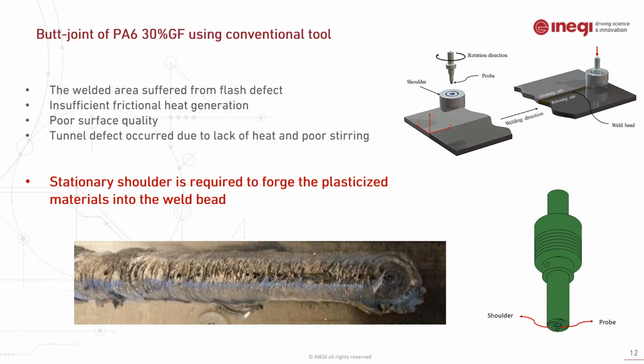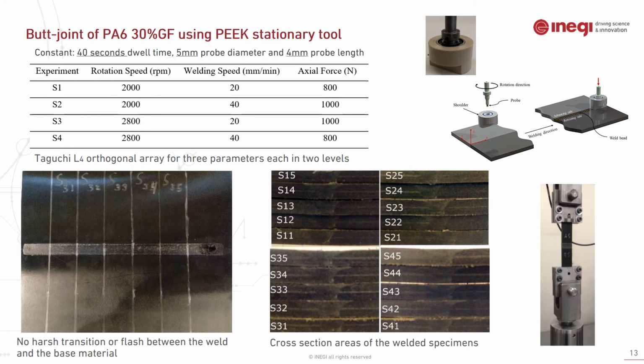In general, it was concluded that the conventional tool, which has a rotating shoulder, is not suitable for welding composites as well as polymers due to the flash defects and bad surface quality in the weld area. So a stationary shoulder is required to forge the plasticized material into the weld. The next tool that was tested was the PEEK stationary shoulder that was developed for welding polymeric material.